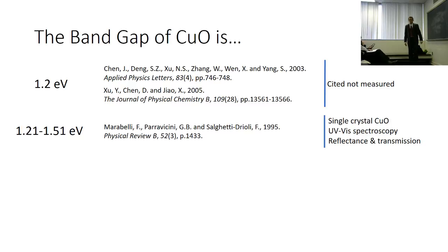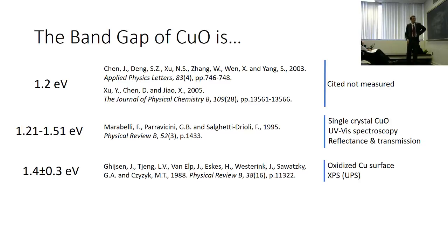Great, but I just wanted to make sure, so I wanted to get one more source. Maybe who knows what they're doing. I found another source that said the band gap of copper oxide is 1.4 electron volts, plus or minus 0.3. They used oxidized copper surface — heated copper and oxygen to make copper oxide and did ultraviolet photo emission spectroscopy, a different way of measuring band gap. But this is a pretty big range, 1.1 to 1.7 — that's basically all the materials I showed before.